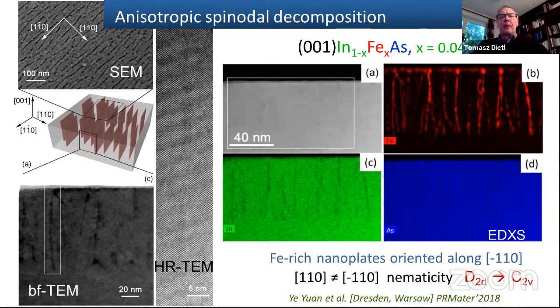And you look again for crystal structure, you see a very well arranged zinc blende structure, but if you have chemical sensitivity, you see that actually iron arsenide forms nanoplates perpendicular to the plane, which grow along the growth direction and are oriented about the 1-1-0 direction. So there is kind of anisotropic spinodal decomposition. One of the axes is preferred by this arrangement of these nanoplates compared to the other.